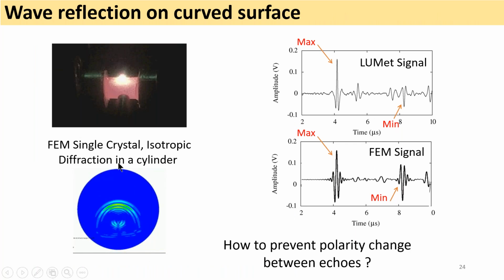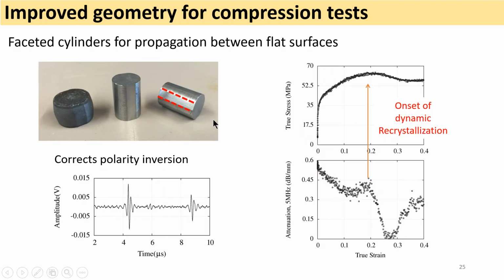So here is a quick illustration of what's happening for a wave which propagates into a cylinder. You can see that it's a complex propagation mechanism which consists of constructive and destructive interference, and sometimes the waveform can be very tricky to analyze. What you can see here is that if we simply use a cylinder specimen, we have a reversal in the polarity of the echo, which can sometimes cause a problem in the measurement of attenuation. I just show you this to give you a hint of what we have done to try to improve this type of measurement. We've simply machined small facets on the sample to make sure that the wave would be generated and reflected on flat surfaces. The result is a waveform which is much cleaner and easier to analyze, and so we could go further into this type of measurement.